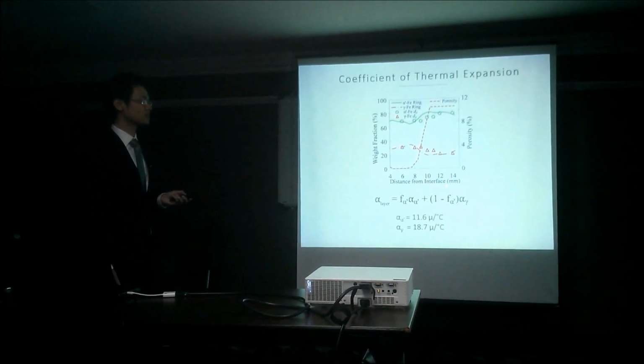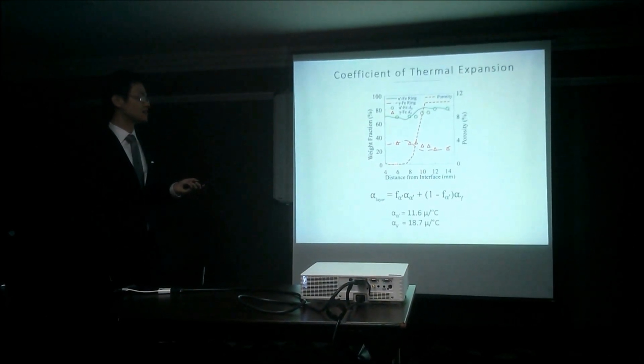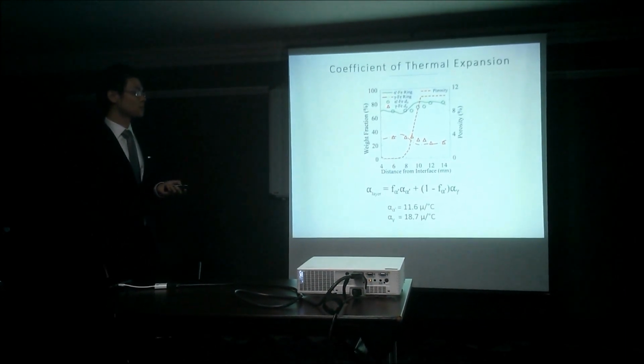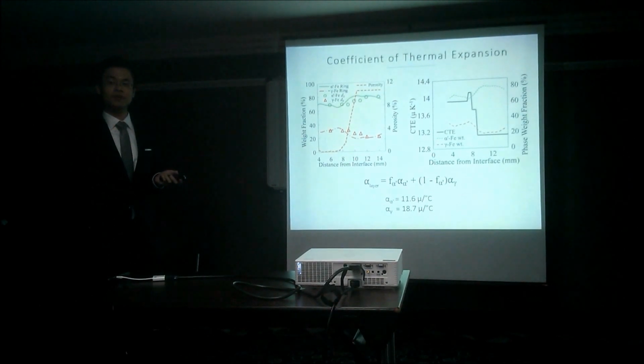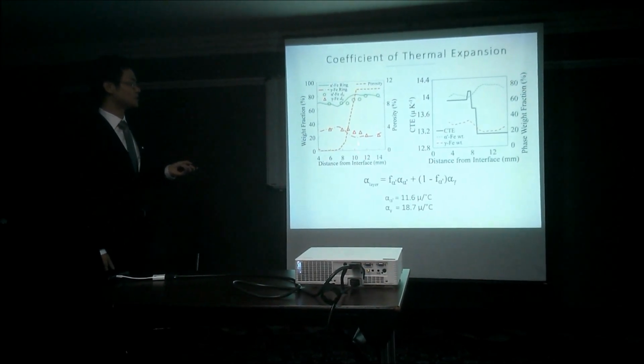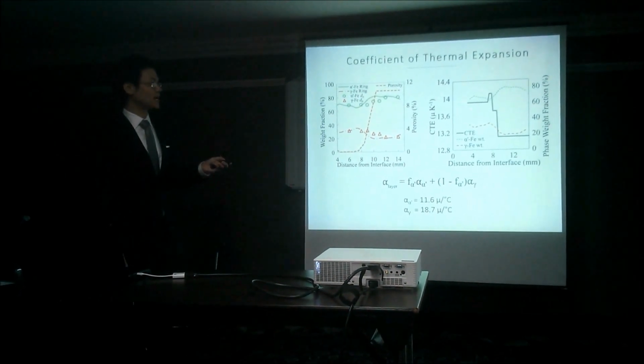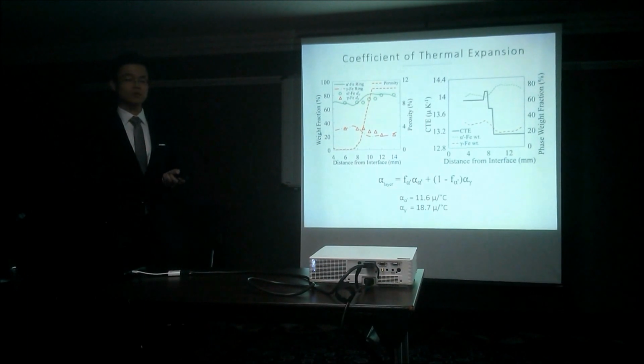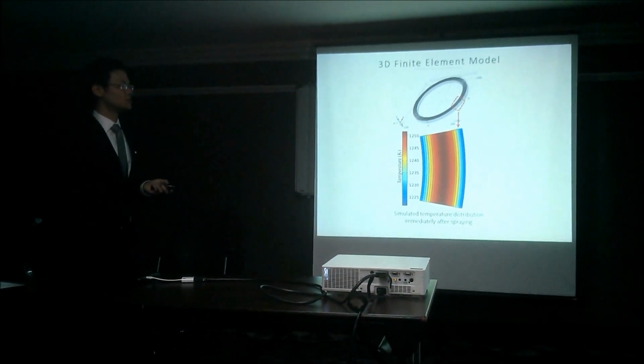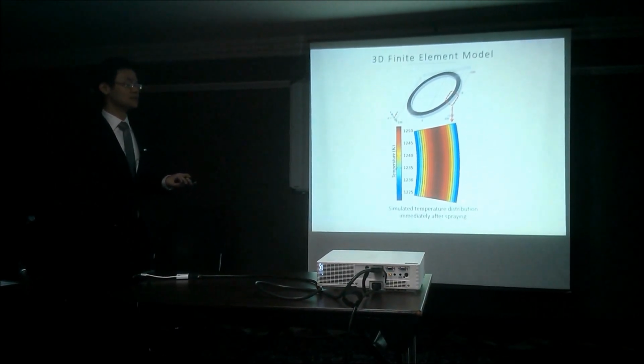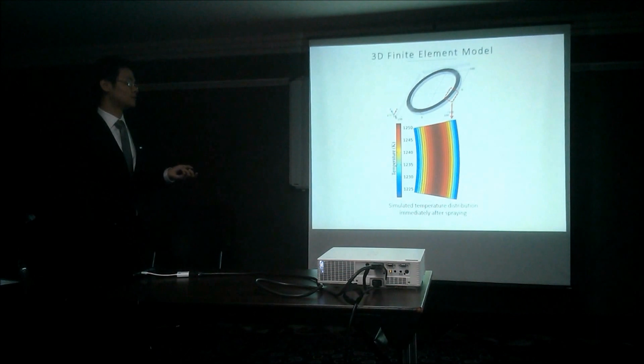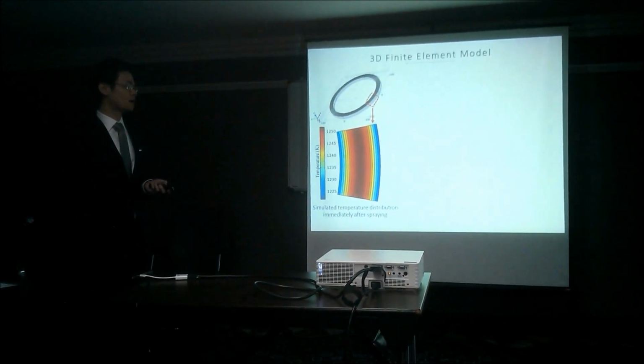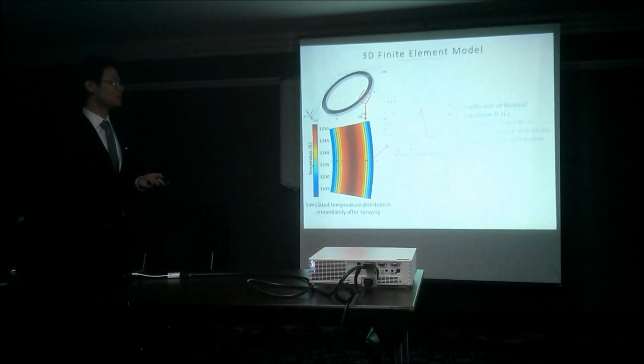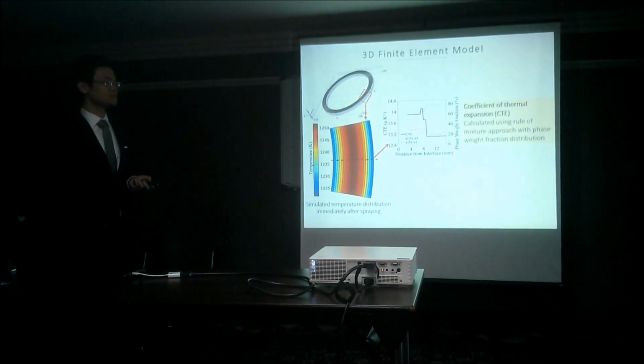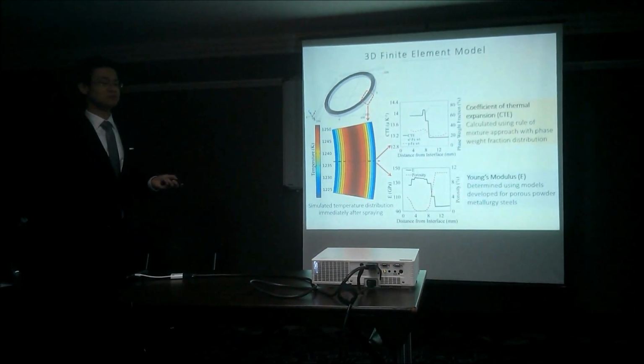So in our sprayed steel, we have a distribution in phase weight fraction. And we discretize the thickness of the sample. And using a rule of mixtures, we calculated the effective coefficient of thermal expansion for each layer. And therefore, we get a CTE distribution. We then developed a 3D finite element model to help us simulate the thermal history and the temperature distribution across our ring sample. And in our model, we incorporated the measured and calculated CTE distribution in addition to the physical properties of the materials.